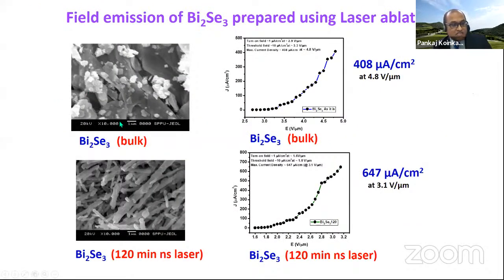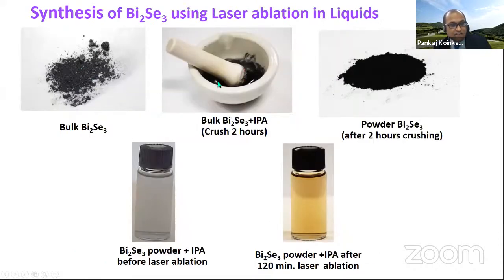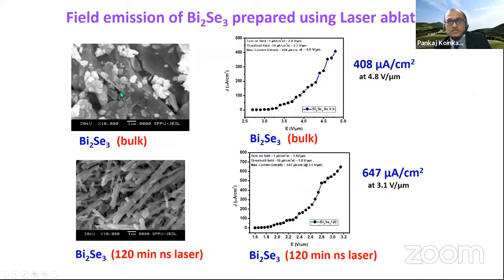So this is the bulk material, and this is the laser ablated. After 2-hour ablation, you can see these are sheets. Since we crushed the sample, in the bulk sample there are some small particles and some big ones. When we crush, the smaller particles become even smaller, and maybe these bigger particles still remain as sheets of 1 to 2 micrometers or several micrometers in size. But there are some sheets of 500 nanometers, since the bulk material is not uniform. But after laser ablation, you can see rod-like formation occurs in the case of bismuth selenide.